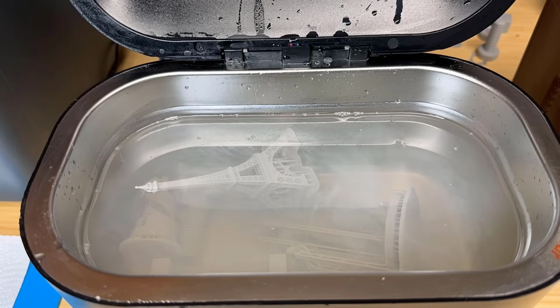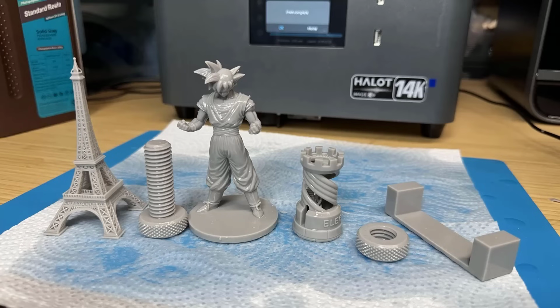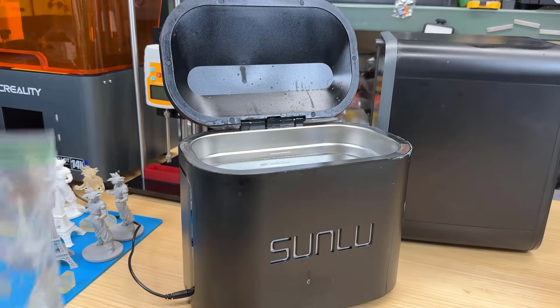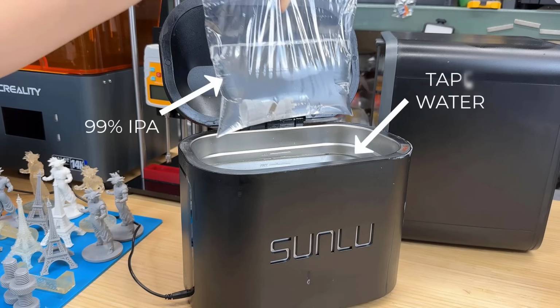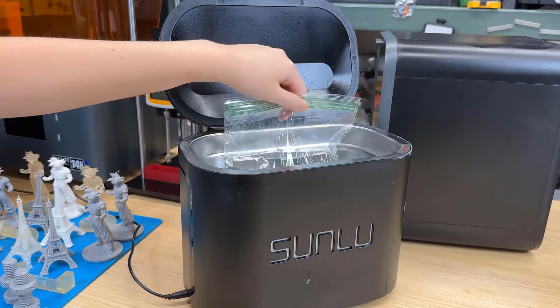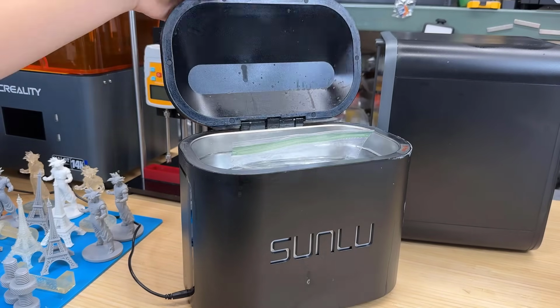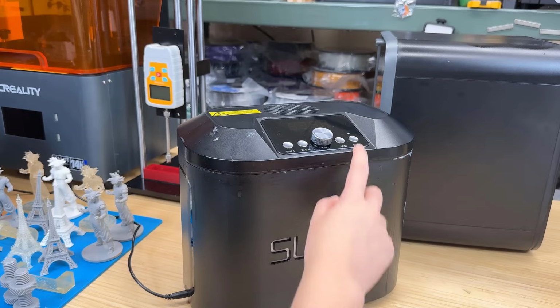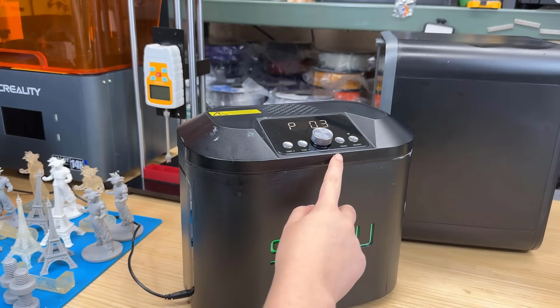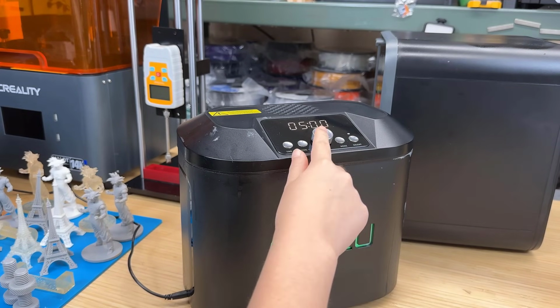For the ultrasonic cleaner, it might work better for models with small gaps like the Eiffel Tower, but for general decorative models, I didn't notice any difference compared to using a resin washer. However, there's a tip for saving IPA or resin detergent when using an ultrasonic cleaner. You can place the model inside a Ziploc bag filled with IPA. The ultrasonic waves will still clean the model inside the bag, but you can save a lot of IPA and avoid the hassle of cleaning the machine before using it to wash jewelry or other items.